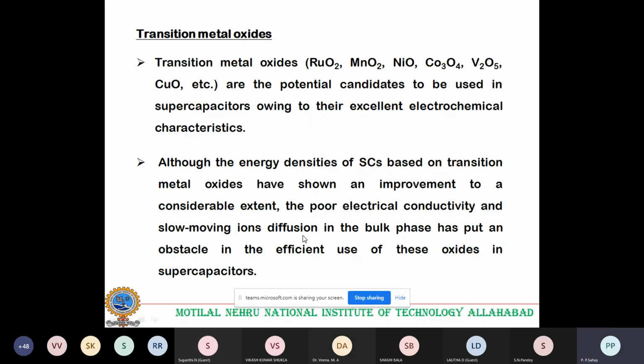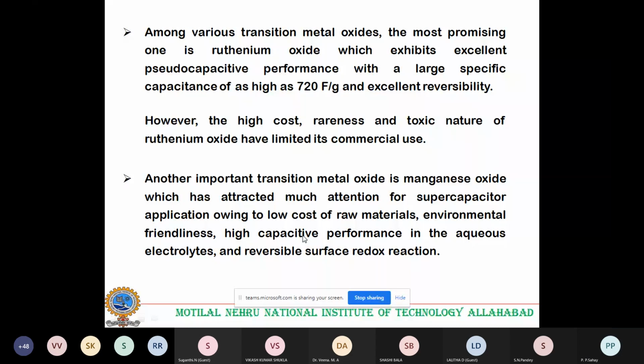Among various transition metal oxides, the most promising one is ruthenium oxide. A lot of work has been done on ruthenium oxide, which exhibits excellent pseudo-capacitance performance with a large specific capacitance as high as 720 farad per gram and excellent reversibility.